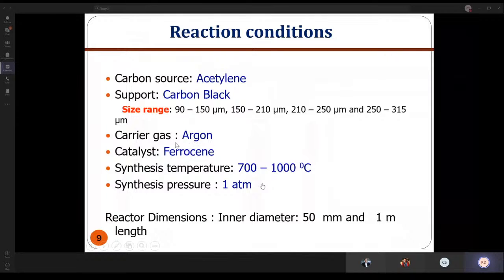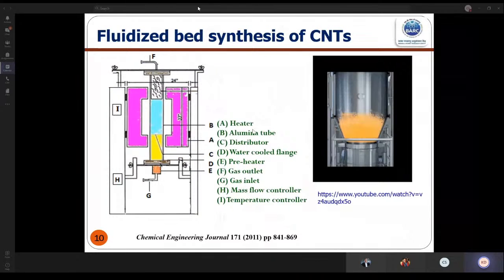We require a carrier gas. We have used argon as the carrier gas. A catalyst is required. Ferrocene is an organometallic catalyst, which on decomposition gives iron nanoparticles, onto which the carbon nanotube is formed. And we have employed a synthesis temperature of between 700 to 1000 degrees centigrade at atmospheric pressure. And this is the typical furnace, and I'll just show what fluidization means.